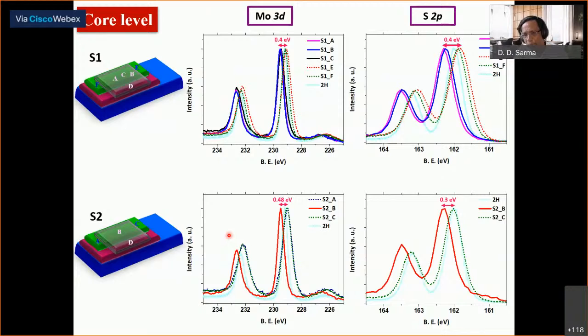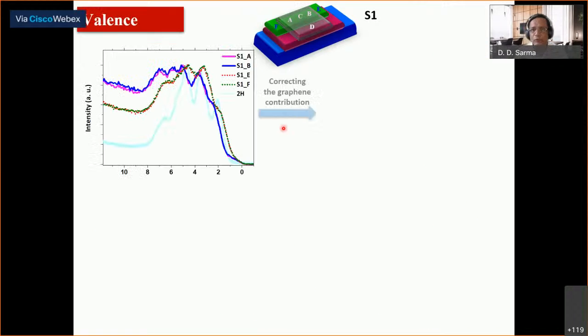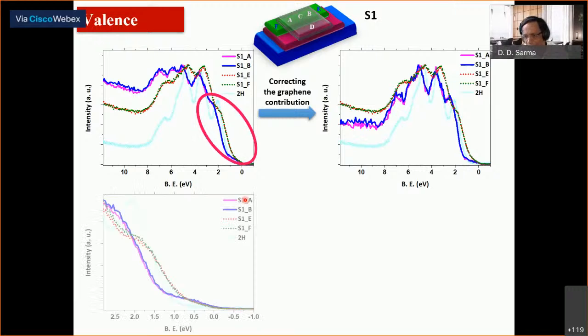In this sample also, approximately similar shifts we see. And remember, it cannot be because of a charge transfer from sulfur to molybdenum, because then they would have shifted in different directions. But the sense of shift is always the same. Heterostructure has a higher binding energy of about 0.4 electron volt. Not only the core levels, we have looked at the valence band also, since I'm running out of time and I want to leave some time for discussion.